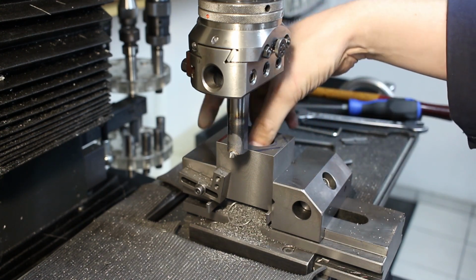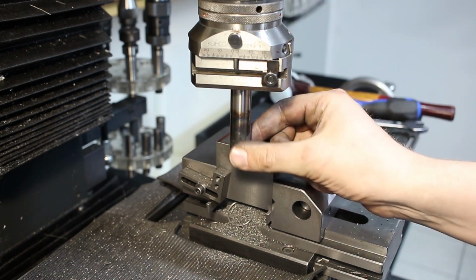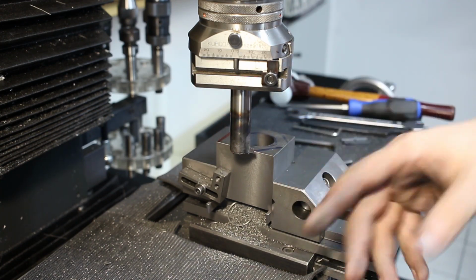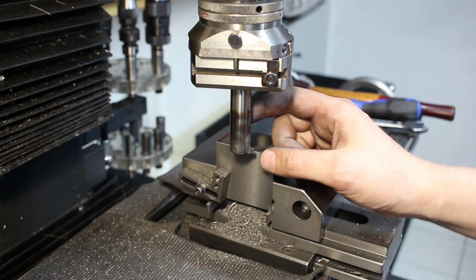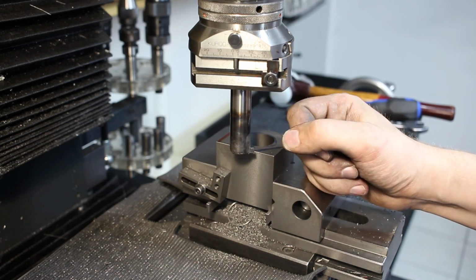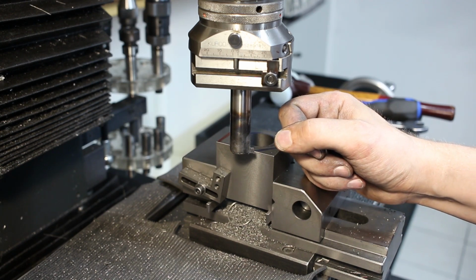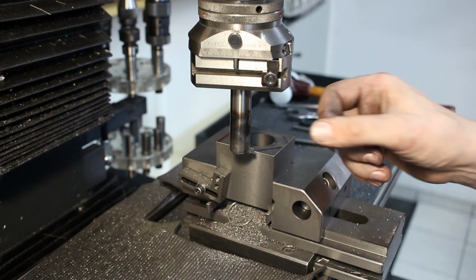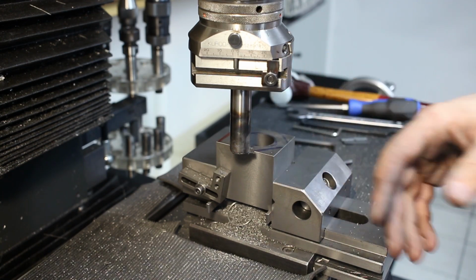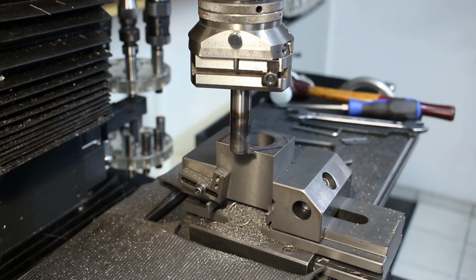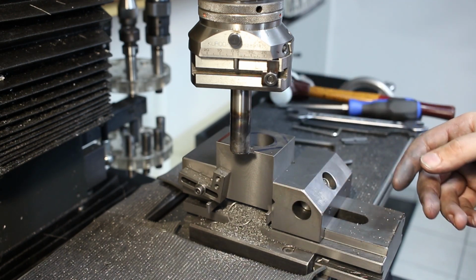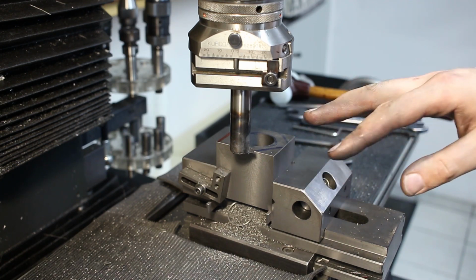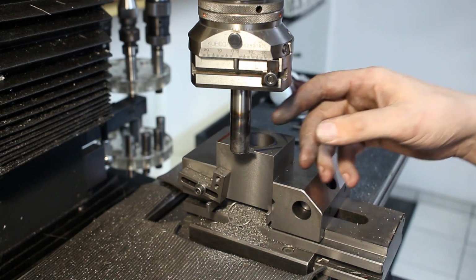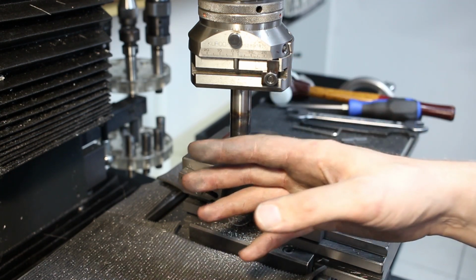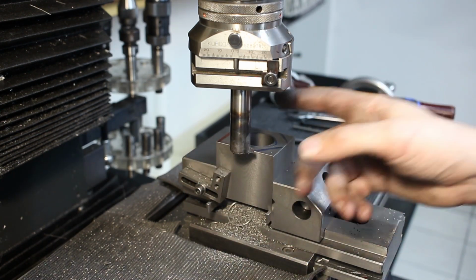The relatively fine feed per rev and this very stiff large diameter boring bar give a good finish, no vibration, no drama. Keep in mind, no matter what steel you use for the boring bar, as long as it's steel, no matter if it's hardened or unhardened, the modulus of elasticity is always the same, so the boring bar always deflects the same. No matter if it's mild steel, hardened tool steel, or in this case hardened linear shaft, it's always the same deflection under load. What changes is the load that you need to deform it permanently, but that's not interesting in this case. We don't want to bend this.